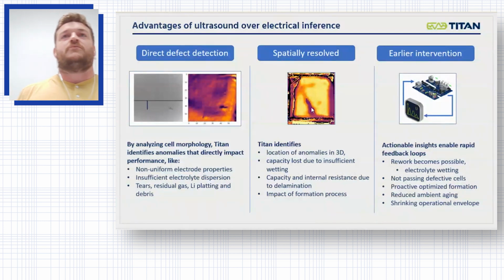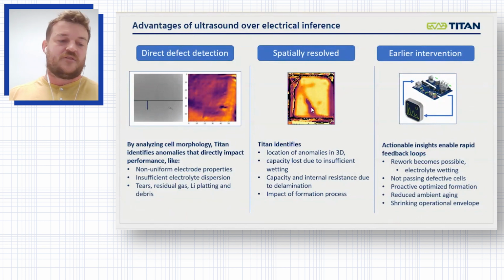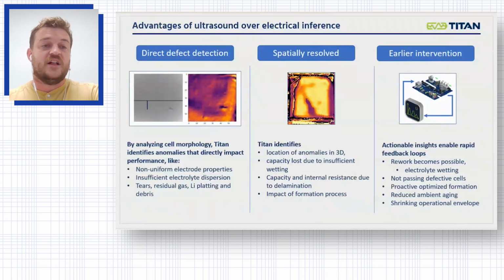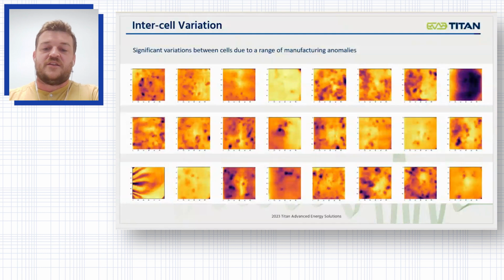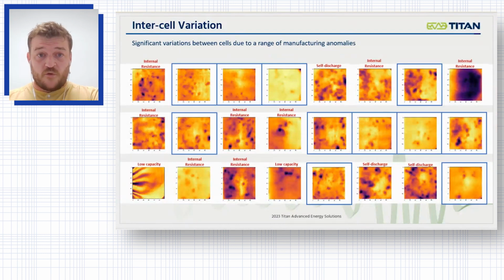That turned out to be a wrinkle that then caused a cascading effect in the surrounding region, hampering the performance of the cell, causing reduced capacity overall. And this was pretty cool stuff. And so now we've been expanding our portfolio of cells we've been able to scan, proving our capabilities. And this is what we presented in the International Battery Seminar in Orlando. And we can go forward, we can see a bit more interesting stuff going on.